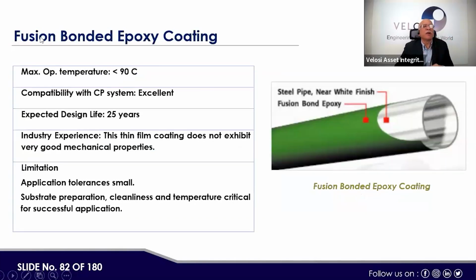Next is the fusion bonded epoxy coating. Maximum operating temperature could be less than 90 degrees Celsius. Compatibility with the CP system is excellent. Expected design life is 25 years. Fusion bonded epoxy, industry experience: this thin film coating does not exhibit very good mechanical properties. Limitation: application tolerance is small. Substrate preparation, cleanliness, and temperature are critical for successful applications. Here, like a fusion bonded epoxy coating, this is the pipe, and this is the epoxy bonded.